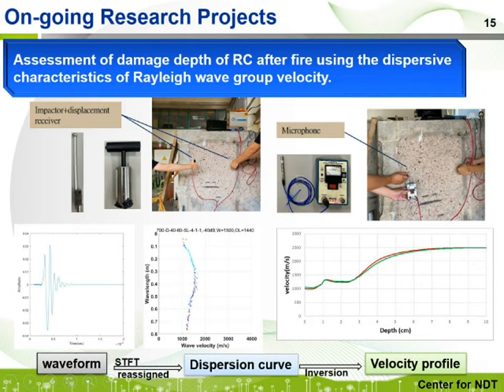For the ongoing research projects, first is the project funded by the Ministry of Science and Technology. In the project, we assessed the depth of the damage for the reinforced concrete after fire using the dispersive characteristic of Rayleigh wave group velocity. We use one impacting hammer and a displacement receiver or a microphone to obtain the Rayleigh wave, and use short-time Fourier transformation and reassignment method to obtain the dispersive curve. And after the proper inversion process, we can get the velocity profile with respect to depth. So the damage depth after fire can be assessed.